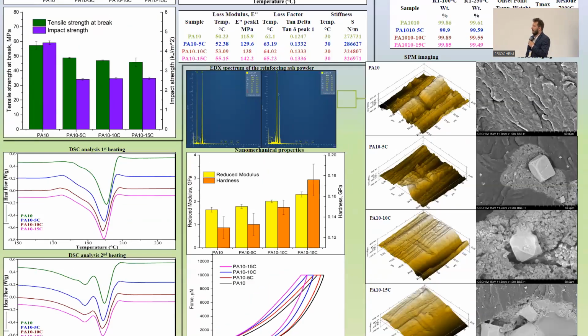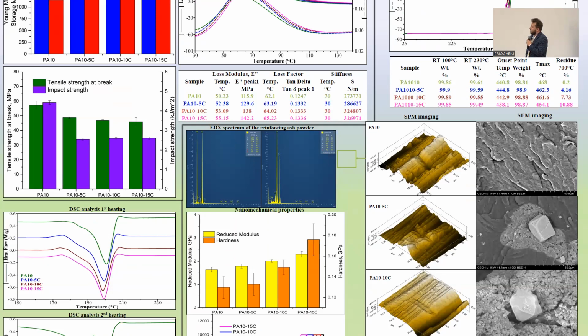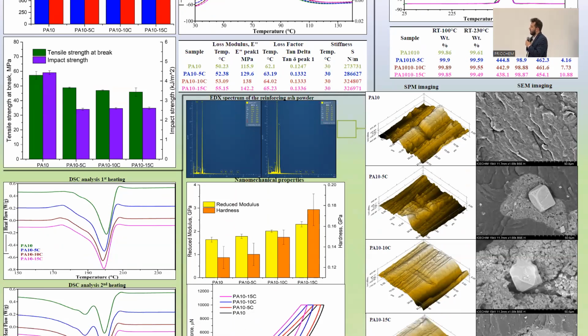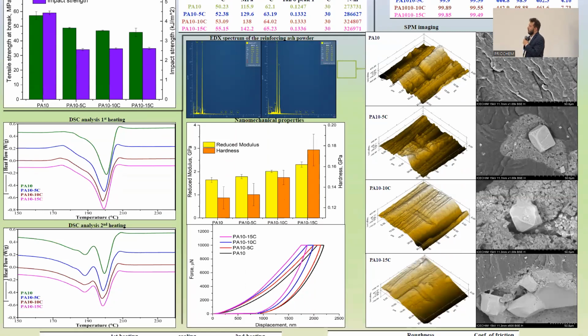to the neat polyamide. The SEM imaging shows the surface of polyamide 1010 and how clean it is, but it also helps us to better indicate the presence of ash powder in our composites. As you can see, if you look really hard, you can see the cubic structures present in each composite. But these large cubic structures are also joined by smaller particles. And through the help of EDX spectra, we saw that the elemental composition of this powder matches the oxidic composition of the ash that we determined before starting this investigation. And so this proves that the ash is present within the polymer matrix.